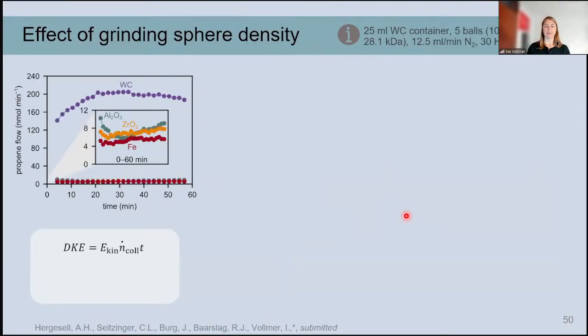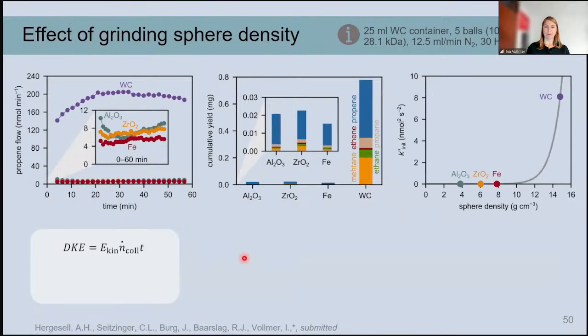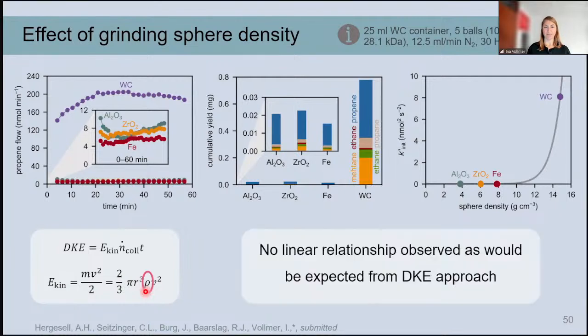And so we also did something similar with changing the density of the grinding spheres. So you can see here that there are some materials which have a very low density, such as steel, zirconia, and alumina. And tungsten carbide, of course, has a very high density. And then if you plot this with the sphere density on the x-axis and the depolymerization rate on the y-axis, you can see that this also does not really look linear. But that's not what you would expect, because the kinetic energy is directly proportional to the density, as you can see here. And so also here, the dose of kinetic energy approach does not seem to work very well.